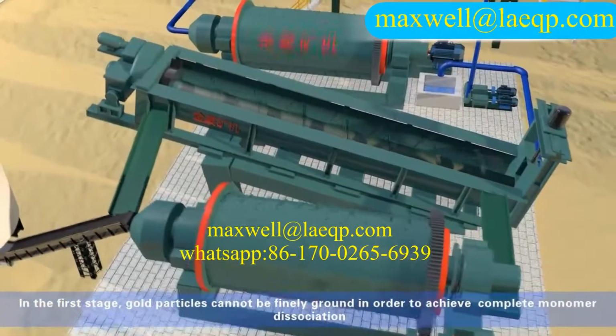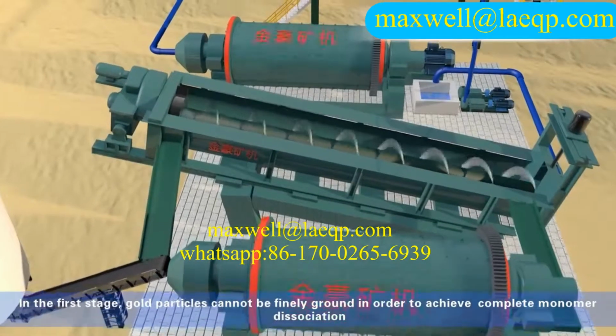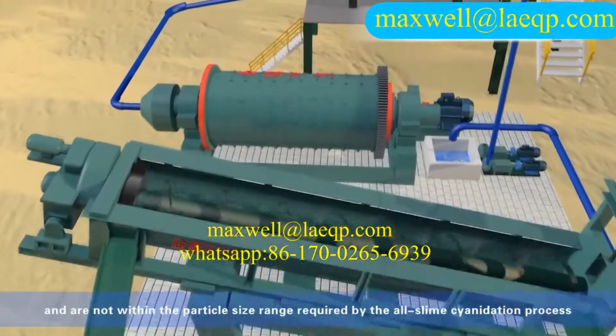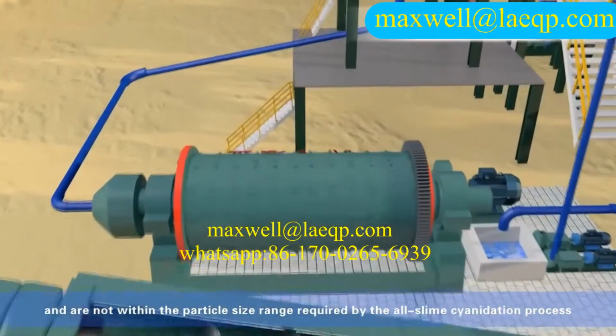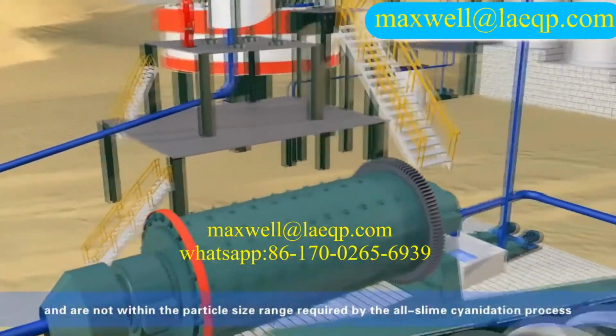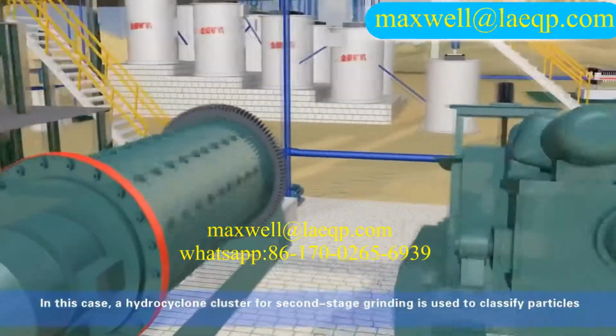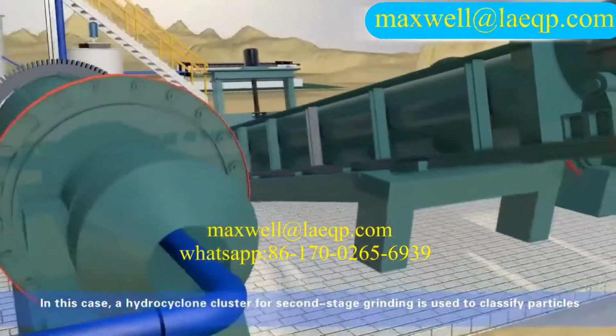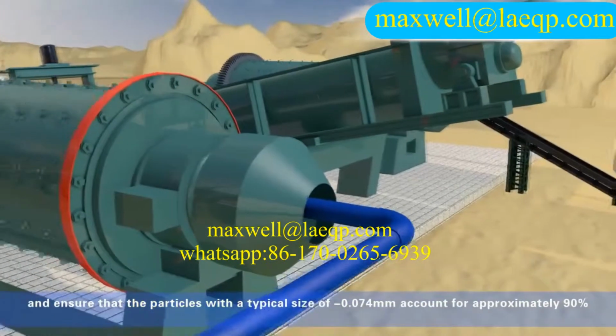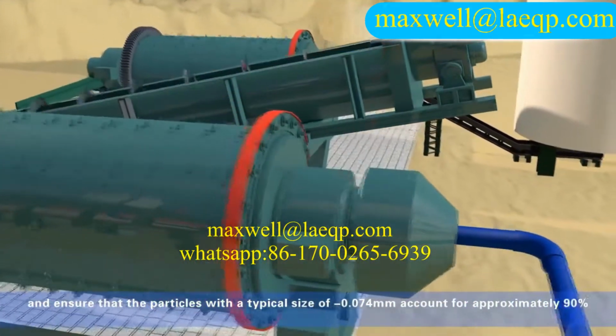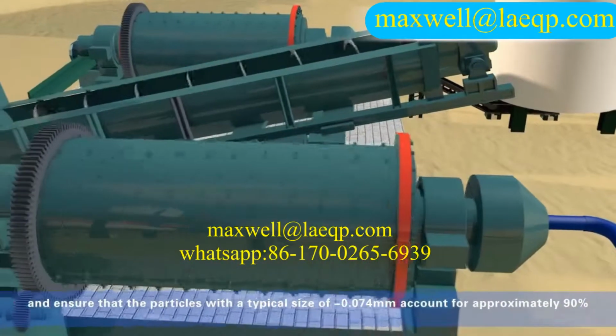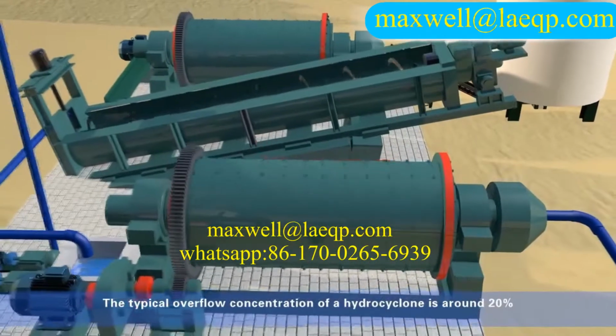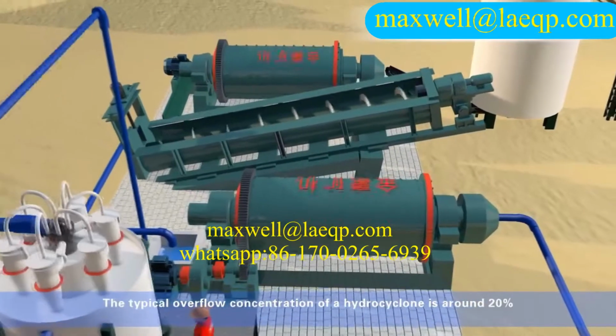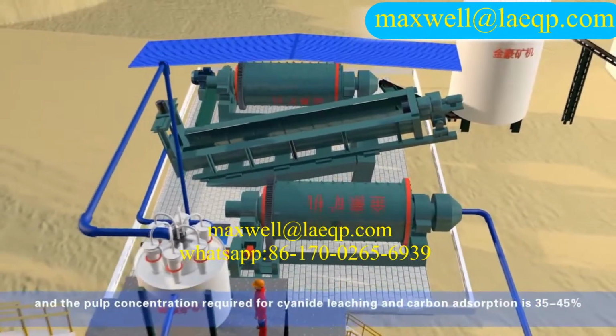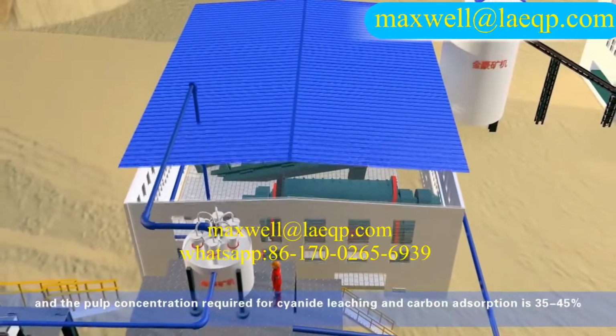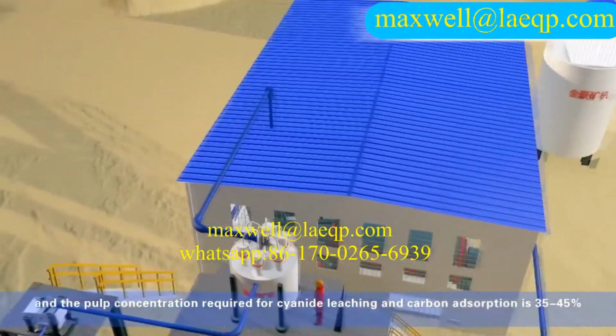In the first stage, gold particles cannot be finely ground to achieve complete monomer dissociation and are not within the particle size range required by the all-slime cyanidation process. In this case, a hydrocyclone cluster for second stage grinding is used to classify particles and ensure that the particles with a typical size of negative 0.074 millimeter account for approximately 90%. The typical overflow concentration of the hydrocyclone is around 20%, and the pulp concentration required for cyanide leaching and carbon absorption is 35 to 45%.